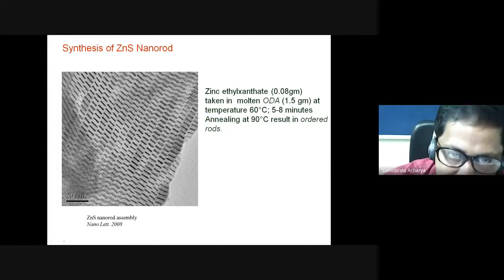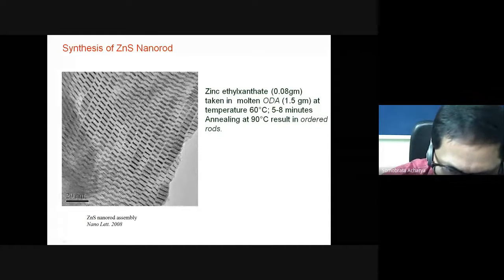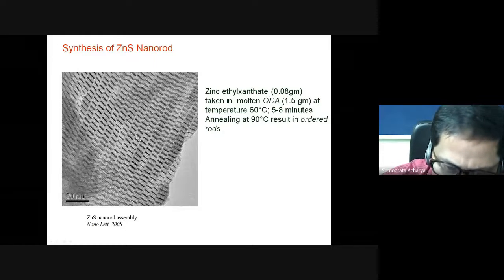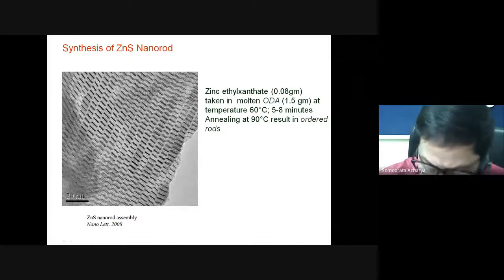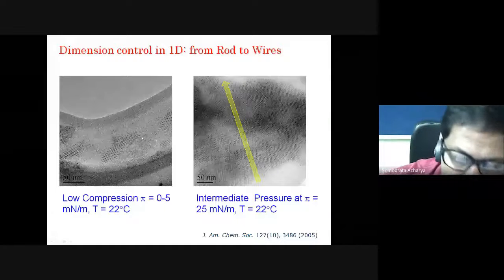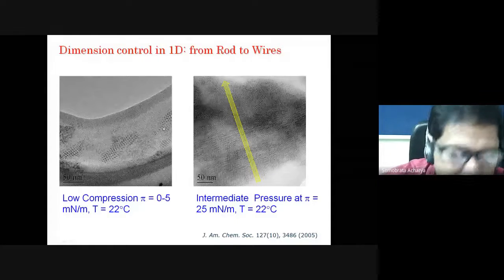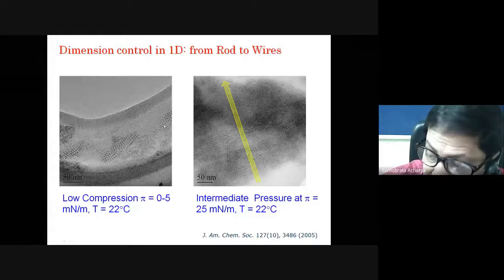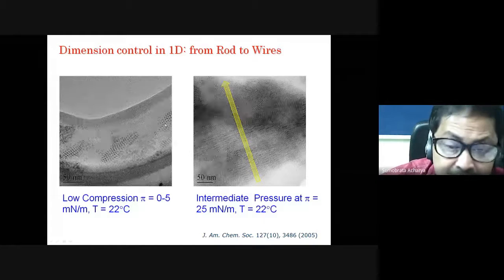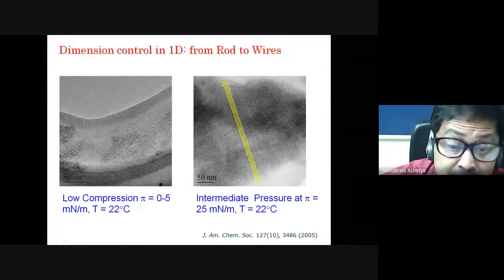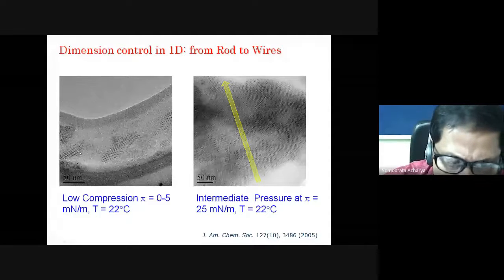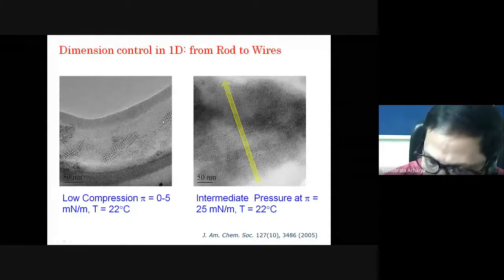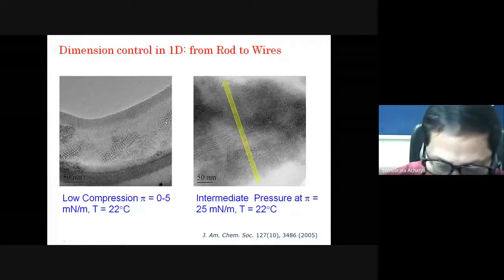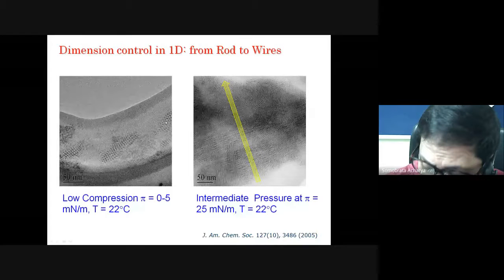So for example, I have taken here the zinc sulfide rods. So these small lines are basically zinc sulfide rods. These are only 1 nanometer in diameter and 5 nanometer in length. So once you spread that at the air-water interface, and if you lift that onto the transmission electron microscope grid, eventually you will see that these nanorods remain in small domains, and there is a large separation between the domains at the beginning of the